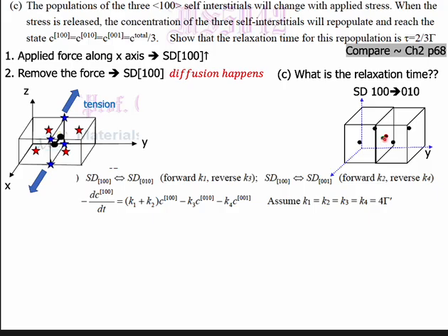As long as this green atom jumps to here, actually the center of the front plane, you will form the split dumbbell 010. Or it jumps to the right, also the center of the front plane. So as long as the green one jumps to the front plane, you can see the split dumbbell changes from the original 100 to 010, the line now horizontal.